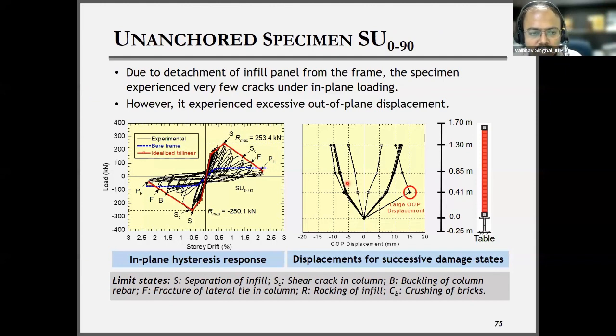There was some improvement in the strength, but no significant improvement. The problem was that the strength after reaching the peak reduced suddenly, and also there was an early separation from the frame.